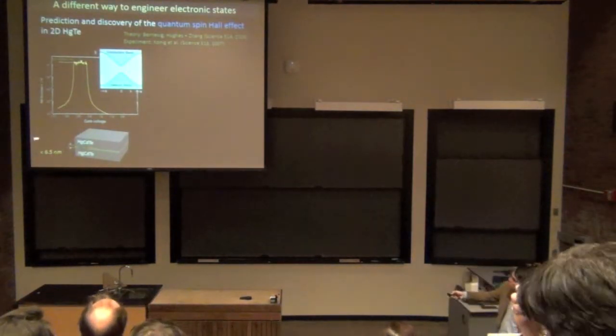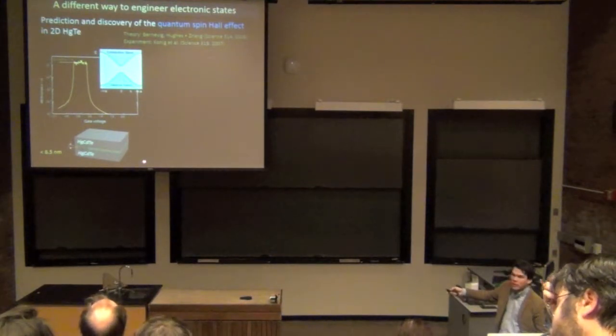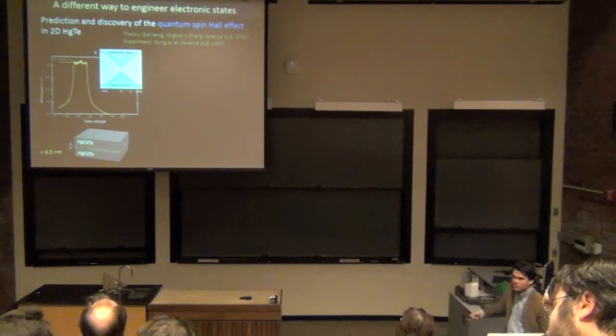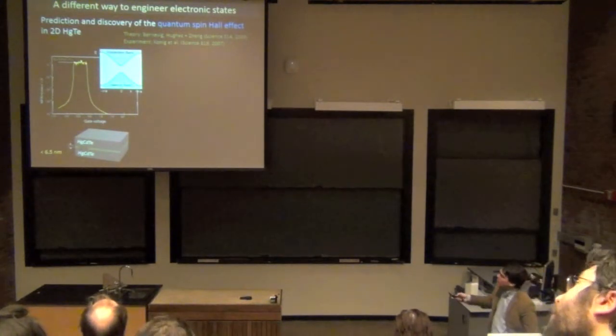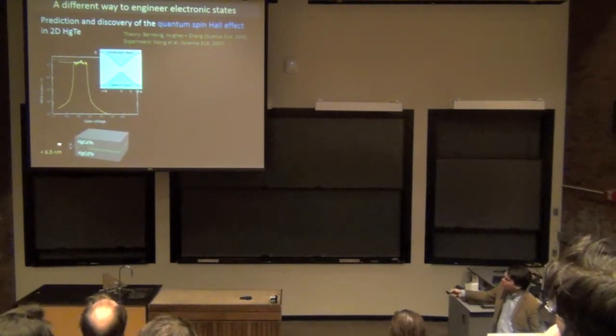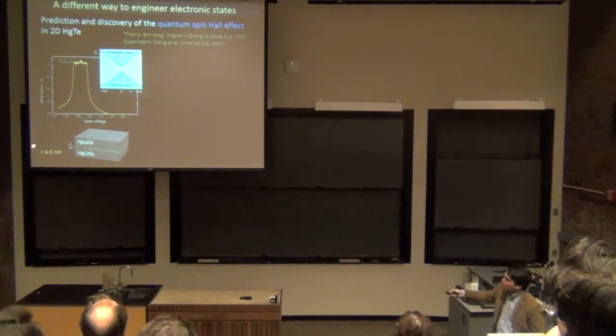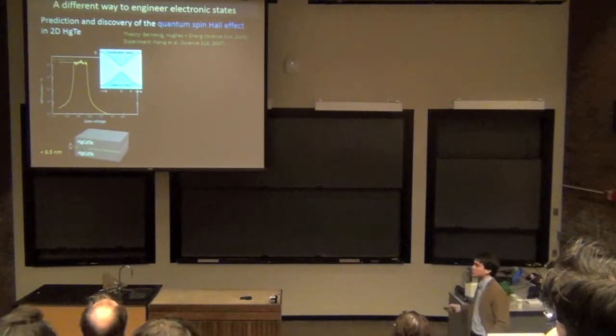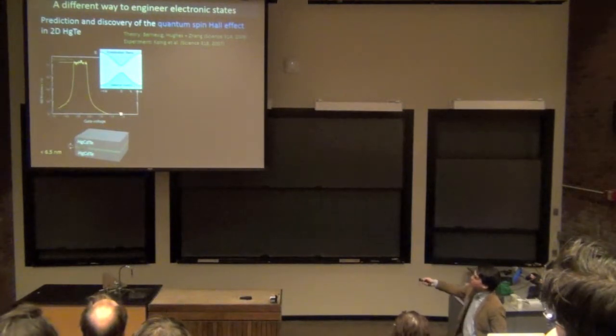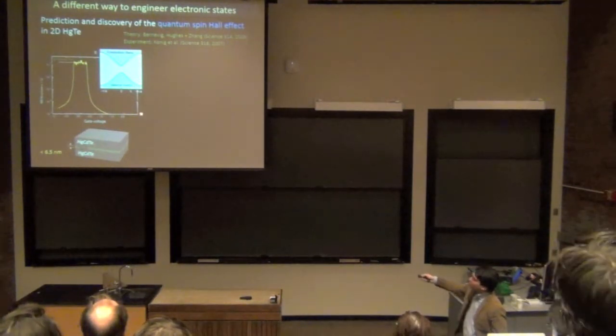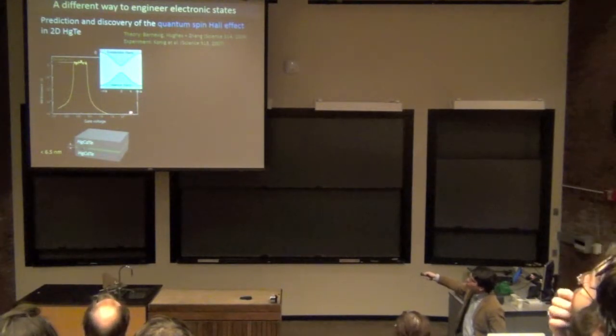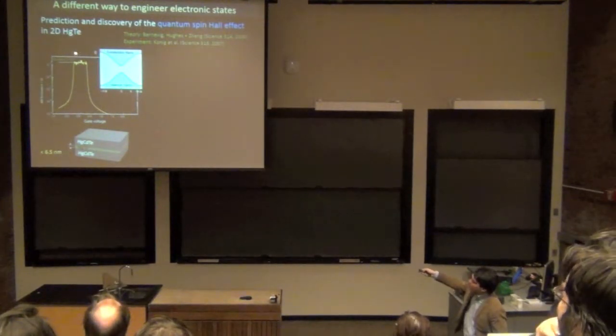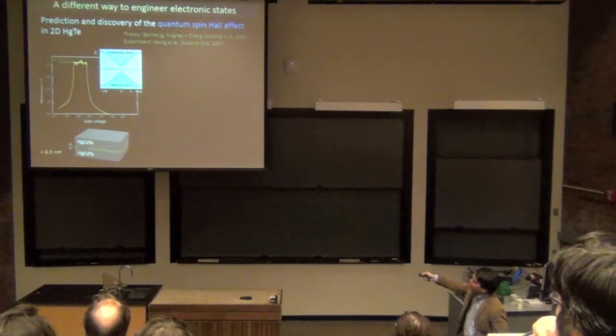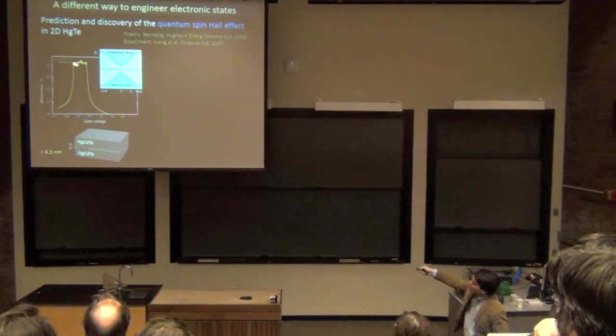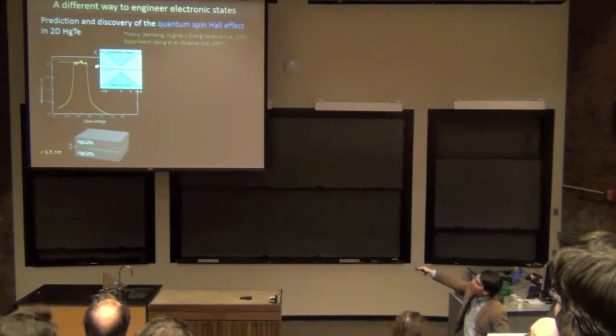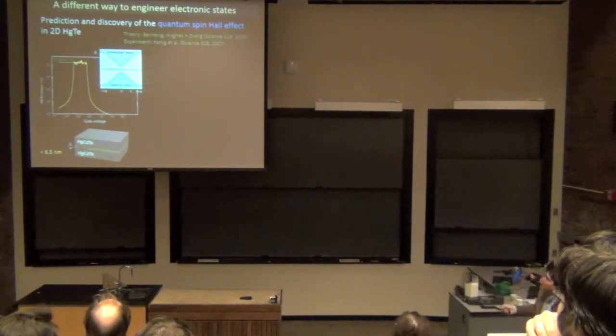So we have a two-dimensional system. This time, instead of gallium arsenide, we make it from mercury telluride, which has a very strong spin-orbit coupling. The really interesting thing is that if we make the width of this well relatively small, it behaves exactly the way you would expect, as a semiconductor. If you tune with a gate voltage, you go from the valence band through the gap into the conduction band, so that if you place the gate voltage right in the gap, you see a very, very high resistance, as you might expect.